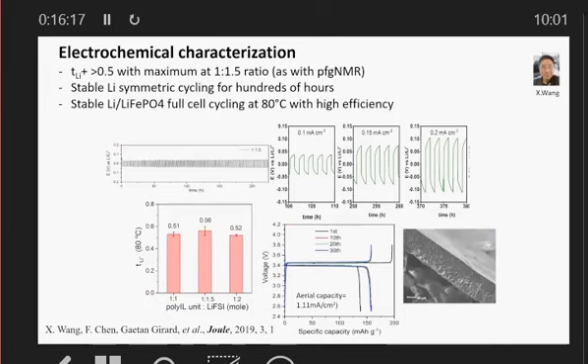I don't have a lot of battery slides in this particular talk, but here is one where we show the performance of these membranes that I showed you before with the optimum composition. If we look at the bottom left-hand slide with the transport number measurements that we measure using the Bruce and Vincent technique, we see that the 1 to 1.5 indeed gives us the highest electrochemical transport number measurement, as well as the highest ratio of diffusion coefficients we saw earlier on.